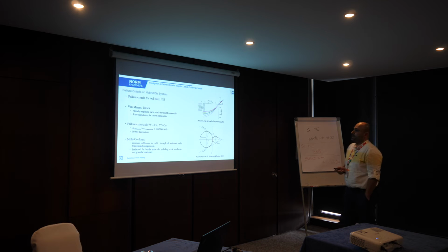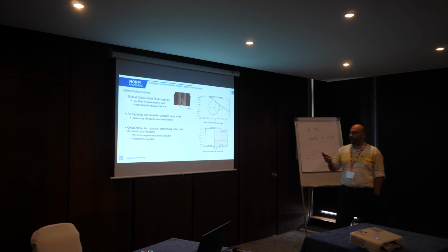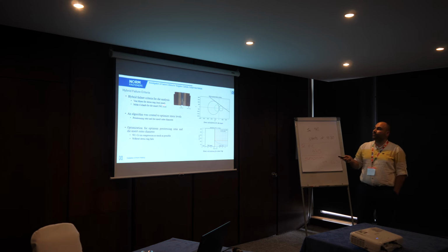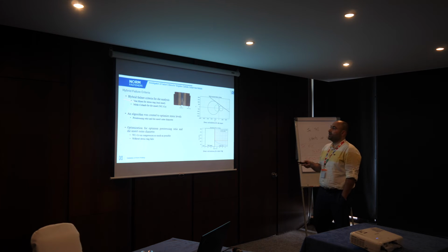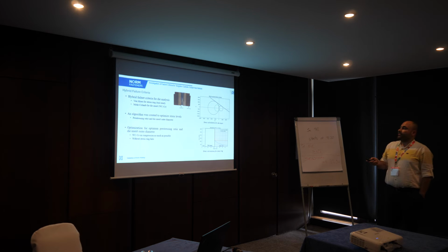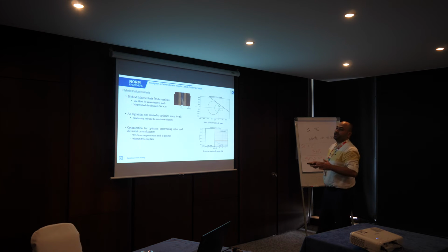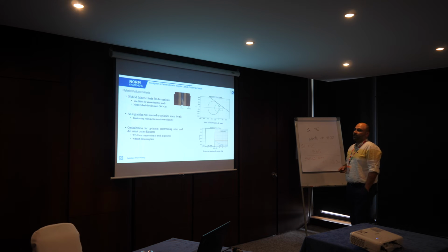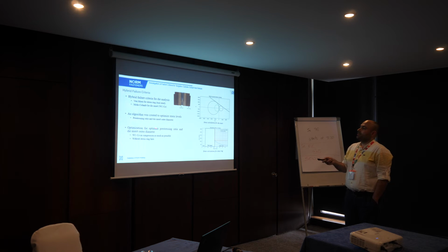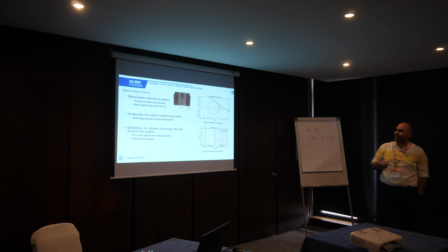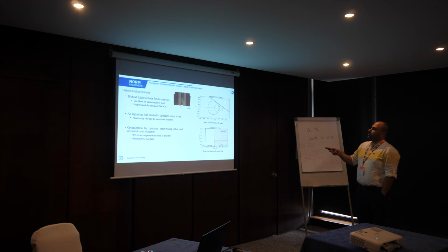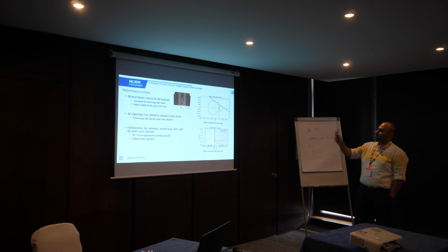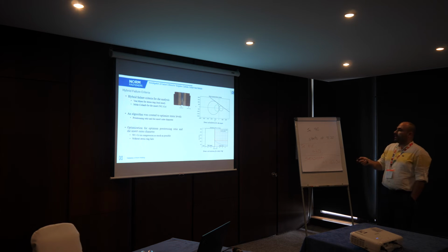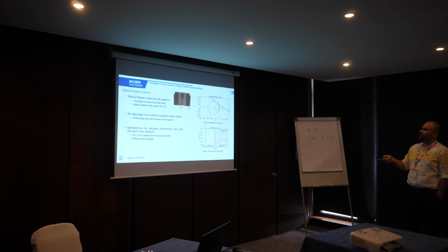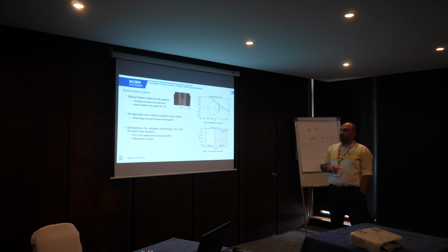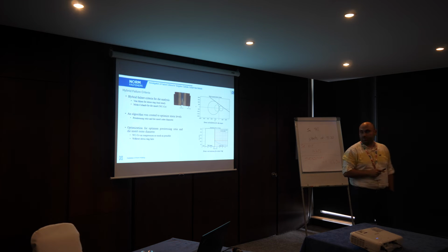So we came up with an idea that we can apply a hybrid failure criterion. For tool steel we can apply von Mises, and for tungsten carbide cobalt we can apply Mohr-Coulomb. So there is another issue. We finally found the failure criteria, but another issue is to find the optimum pre-stressing ratio for this type of dies. So we came up with an idea that this is the Mohr-Coulomb criterion, and this green is the current stress state of the die, and this one is the outer ring or stress ring, for which we apply the von Mises stress criterion.